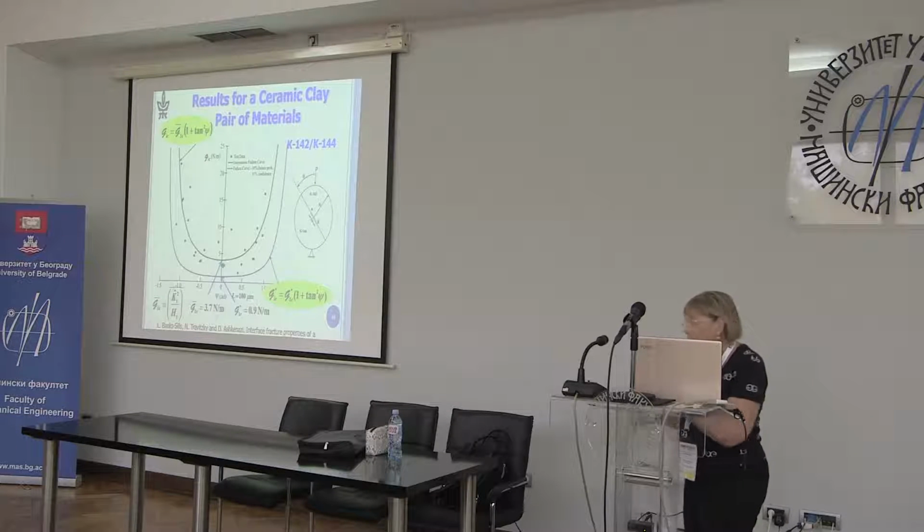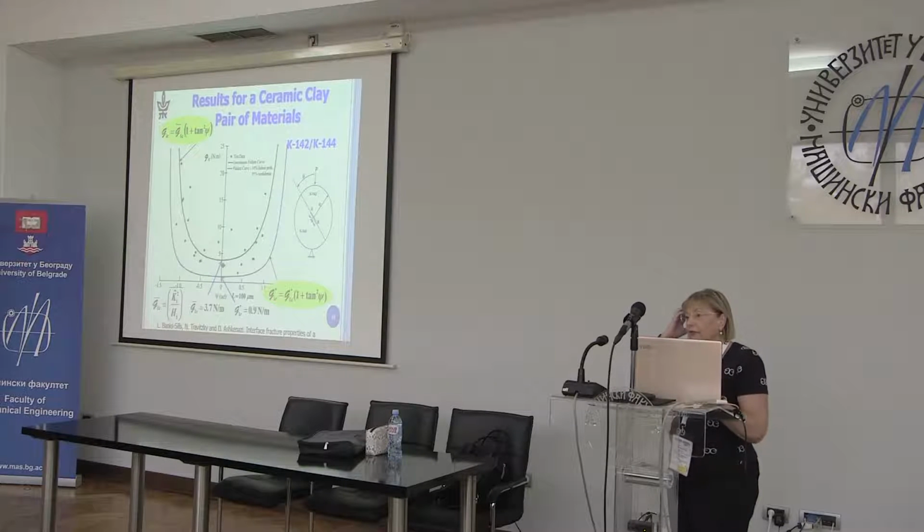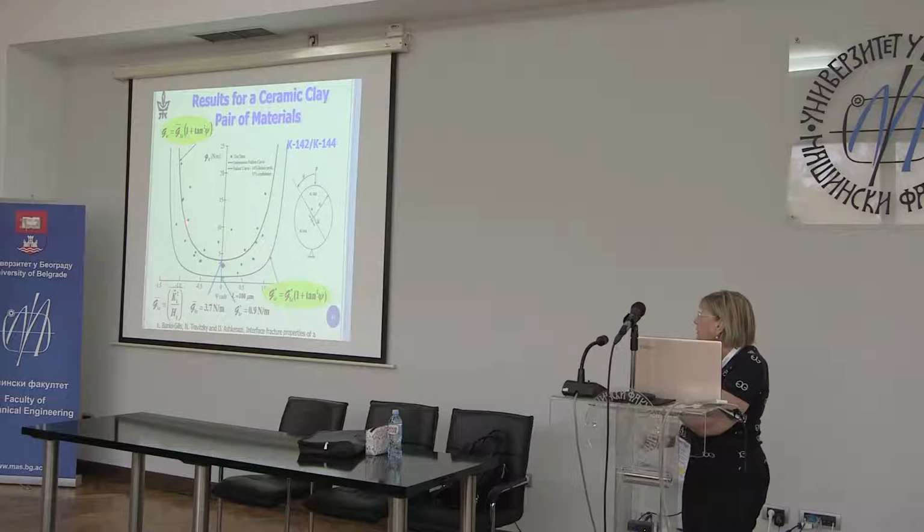And what I didn't say in all of this, but it's written here, here is your L value. And when we first started off, we don't know what L value to choose. We choose an L value arbitrarily, we graph everything, and we see how well the points match up. I showed you an example where they didn't match up at all. And by trial and error, we change the L value until we get something that fits well. It's a free parameter that we can use to make the data fit the curve.